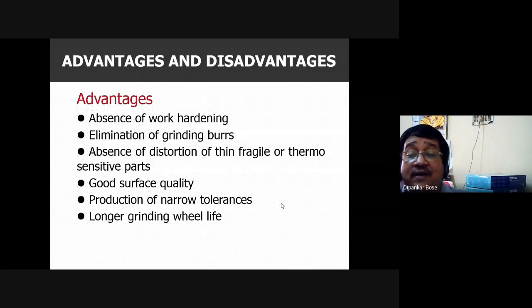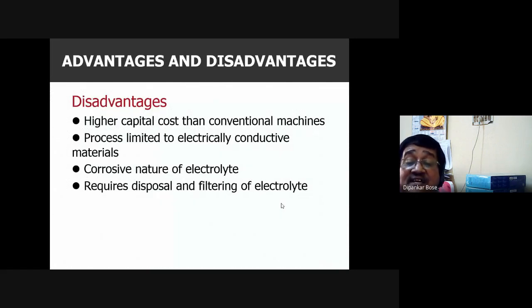What are the advantages? Advantages are too many. No work hardening, no burring, no distortion of thin, fragile or thermosensitive parts. Surface quality is very good, and it can even produce very narrow tolerances and longer grinding wheel life. Disadvantages are there because capital cost is high, and another limitation is that it is limited to electrically conductive material, and the electrolyte is corrosive in nature. And disposal and filtering of the electrolyte is always necessary.